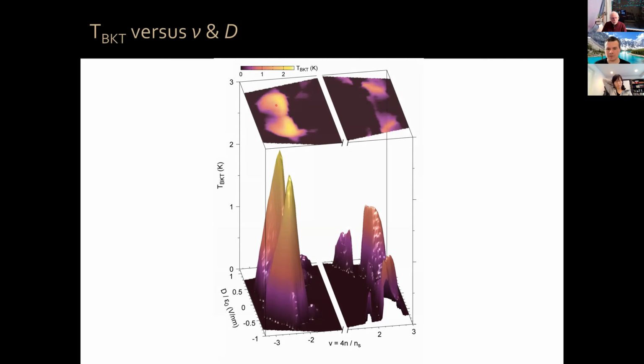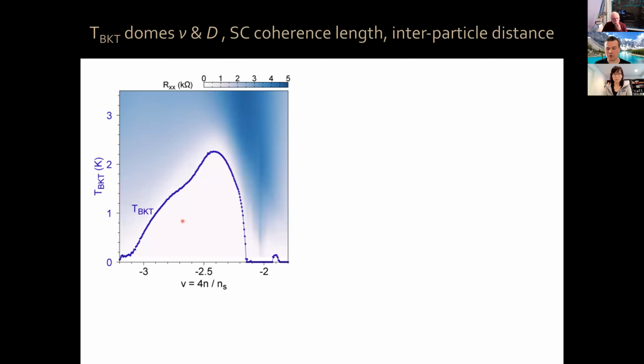As you can see, the superconductivity has the highest critical temperature in this region, as I showed earlier. Because these color plots are a bit complex, let me show you a cut of TBKT as a function of filling factor at optimal displacement field, and then at optimal density, at optimal filling factor as a function of displacement field.